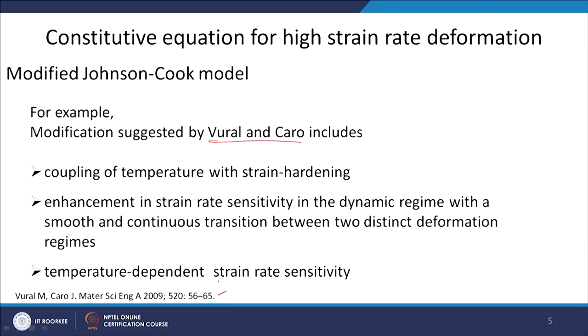Enhancement in strain rate sensitivity in the dynamic regime, with a smooth and continuous transition between two distinct deformation regimes. So, strain rate sensitivity is also going to be affected in the dynamic regime, and there will be a temperature dependent strain rate sensitivity also. So, you should understand that these parameters are all coupled to each other. We cannot treat them independently, and a lot of modifications were proposed by different researchers on the Johnson-Cook model.